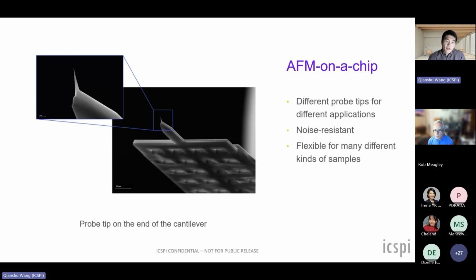So talking about it a bit here, this is a close-up. This is an SEM image of one of our probe tips on the end of a cantilever. This is a diamond-like carbon tip with a tip radius of less than 20 nanometers. We sell a variety of different probe tips for different applications. And here, this talks a little bit about how our AFMs are significantly more noise resistant because they are so lightweight. They automatically reject a lot of low-frequency noise. And we also have very flexible systems that work on a wide variety of samples, which I will talk about a little bit, and then Rob will talk about as well.